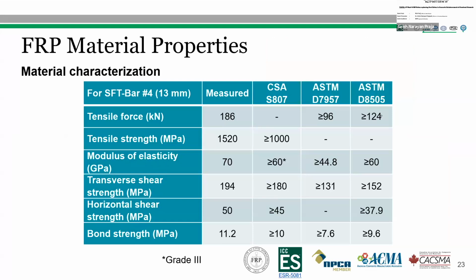For SFTech GFRP bar number 4, the major mechanical properties satisfy all the testing specifications, and the CSA S807 classifies GFRP bars into three categories based on the modulus of elasticity. The tested bar generally came under grade 3, with more than 60 gigapascals modulus of elasticity. And ASTM D8505 is the recently introduced specification to account for GFRP or basalt fiber-reinforced polymer bars with more than 60 gigapascals of modulus of elasticity.